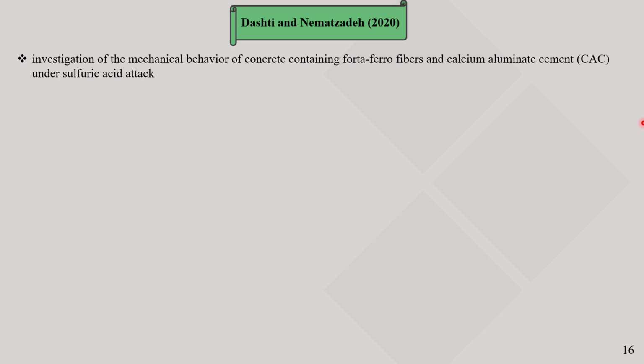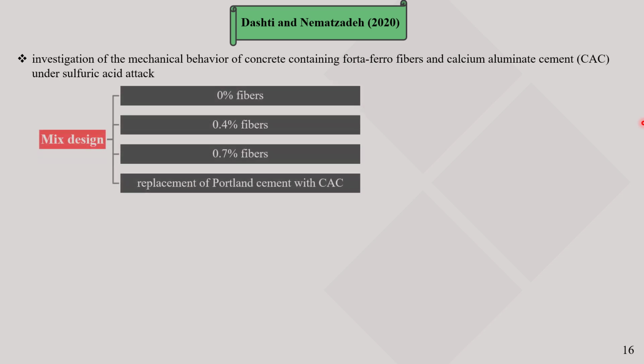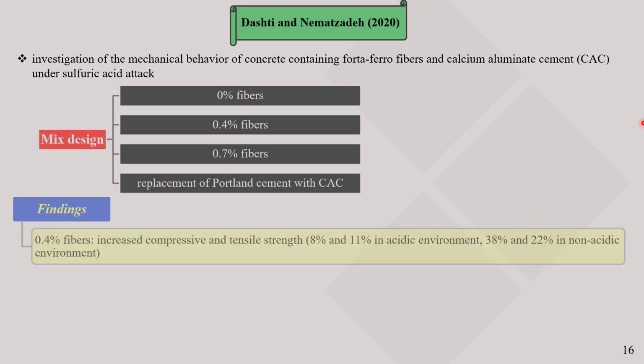The next article was conducted by Mr. Dashti and Nemetsada. They investigated the mechanical behavior of concrete containing Forta-Ferro fibers and calcium aluminate cement, CAC, under sulfuric acid attack. In the mix design, fibers were used at three volumetric ratios, 0%, 0.4%, and 0.7%, and another mix design involved replacing 100% of Portland cement with CAC.